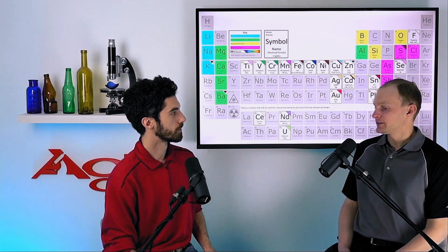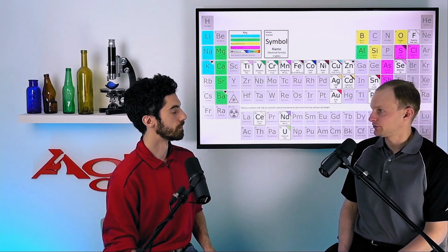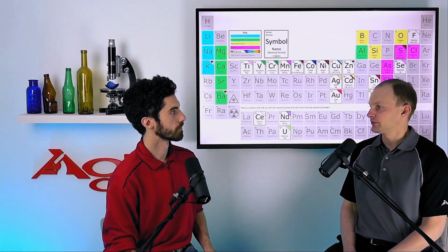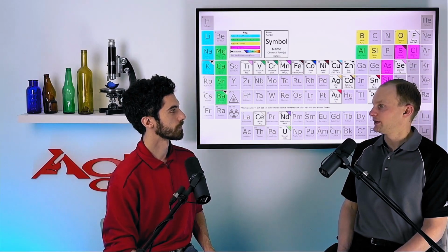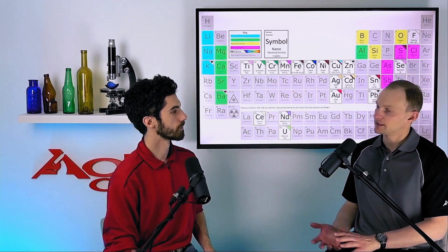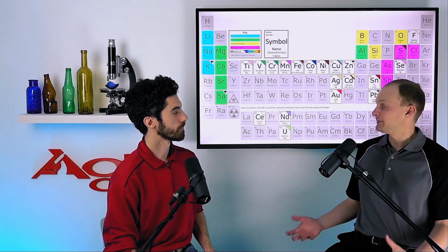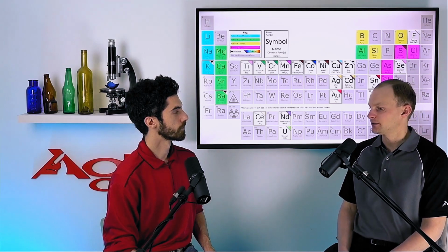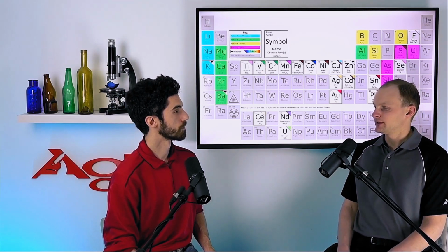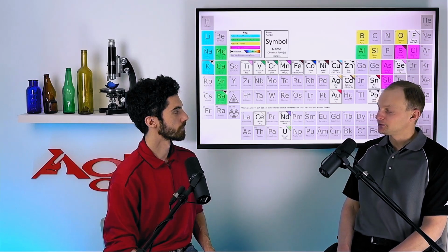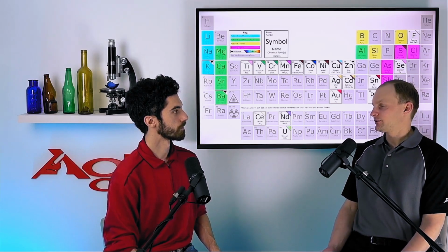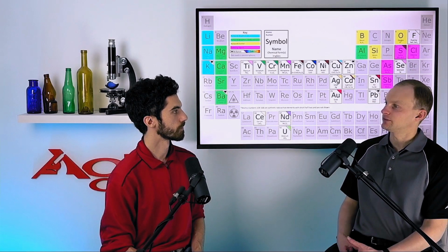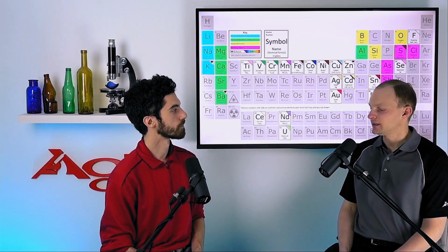And a big one is sand. Monitoring the iron levels in your sand, you want to know that because typically you're very concerned about the color. Certain industries need to know that their iron is below a certain level so that they can be guaranteed of meeting their color spec for flint glass. So there are a lot of different chemical things that can be monitored for this. There are many other types of analytical tests for glass components, such as what's called electrostatic precipitator dust, which is a material reclaimed from the furnace exhaust. That's something they can analyze as well.